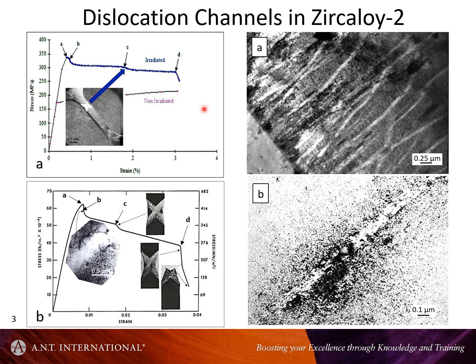So how is this manifested in a bulk specimen? Well, when you get channeling, what you get is a load drop. So if you have a test which is strain driven, when a channel is first formed, it becomes easier to deform, and there's a load drop, as you see here.